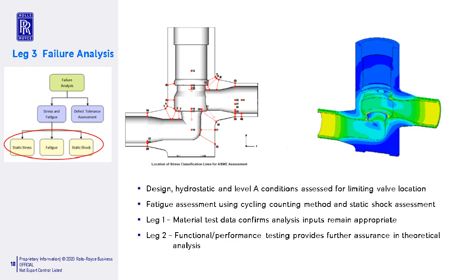So we use the material test data generated in leg 1 to confirm that all the material inputs are still relevant and not undermined. And then we also use the results from the functional and performance tests undertaken in leg 2, just to provide further assurance that the design is sound, and we actually saw this from the tests we carried out in terms of the ultimate pressure test, the shock test and the thermal fatigue test.